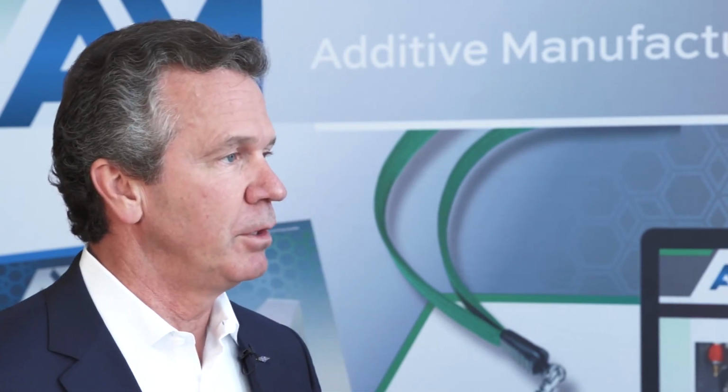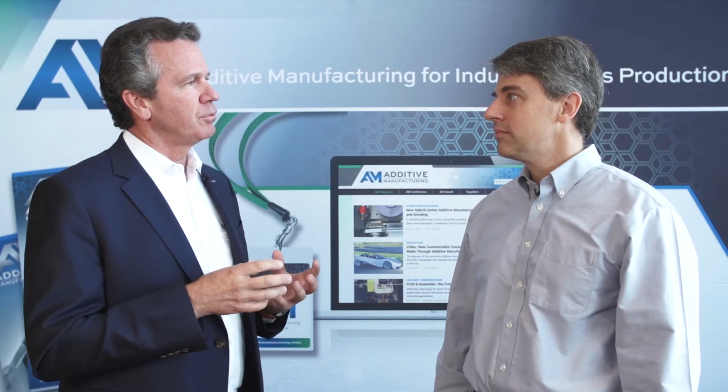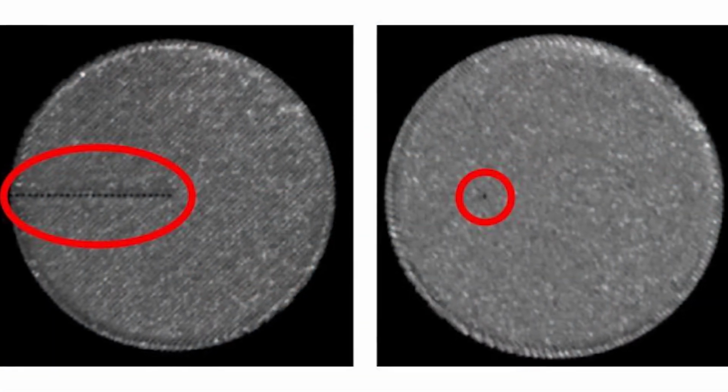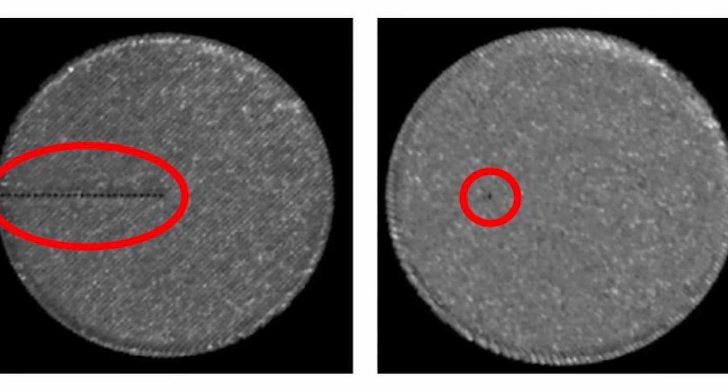So he started with a product called QM Melt Pool, and we've just released the QM Melt Pool 3D. So we're looking directly through the laser into the powder bed, into the melt pool. And we're measuring the intensity of the melt pool as well as the shape and area of the melt pool. We then compress that data, and we produce a three-dimensional model of that entire build. And that'll show if there's any porosity, if the laser went to sleep for 2 nanoseconds. And we're hoping that will help companies be able to certify their parts, whether that's for the FAA or the FDA or any internal certification processes they need. So this three-dimensional model is just another augmentation of the process to give people confidence they're building quality, flaw-free parts.